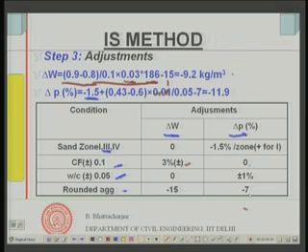Okay. So, 4.9 is the correction in delta P. Then additional correction will come because of the rounded aggregate. It will come as minus 15 kg per meter cube here straight away, and here it will come 7%.